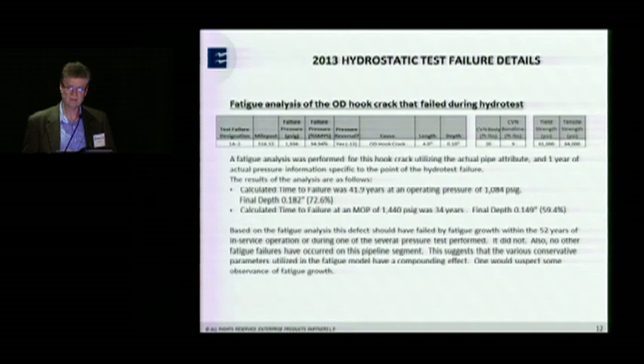And remember, this flaw has been there since day one, so it's been in service 53 years. When we ran the fatigue analysis, we got about 42 years for it to fail, and you'll see that it failed at 1,084 PSI, because that was the actual pressure spectrum. It's going to run it through until it hits that high pressure.